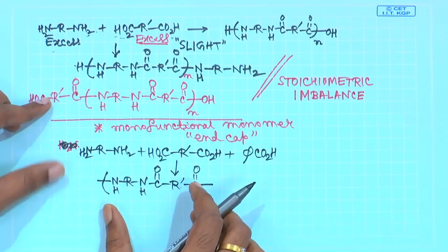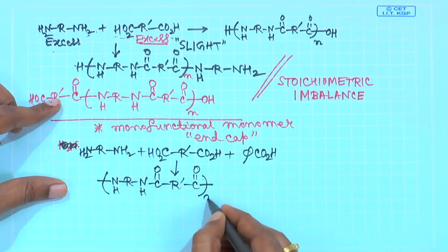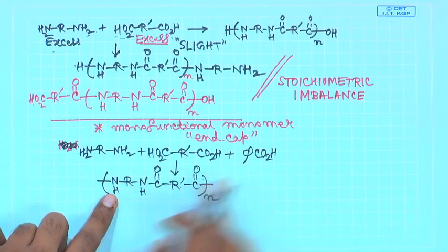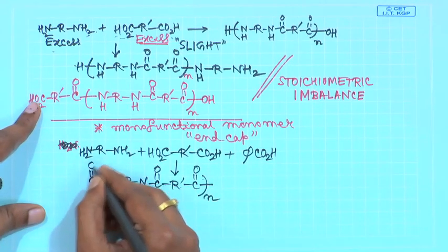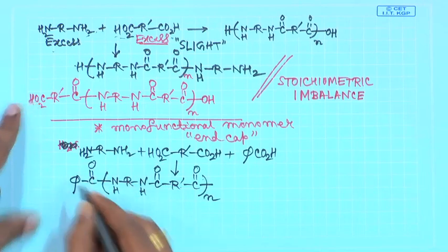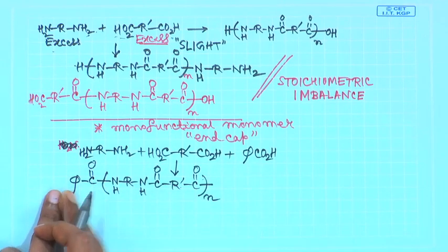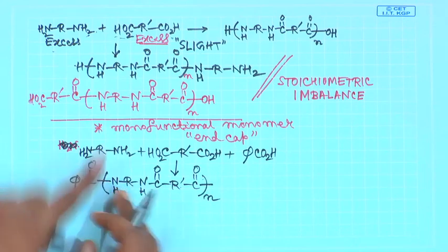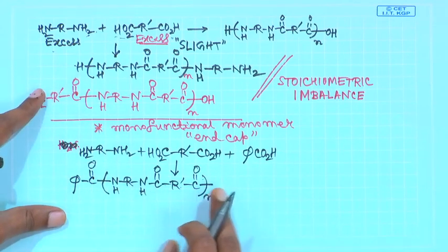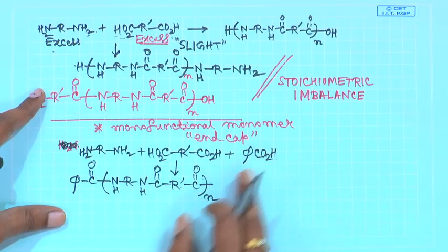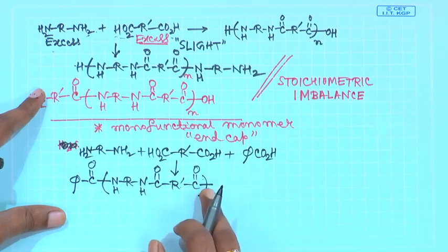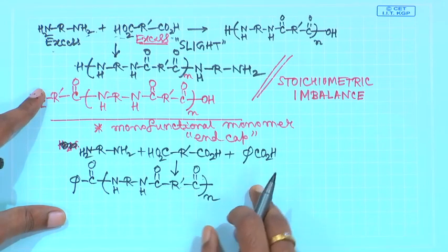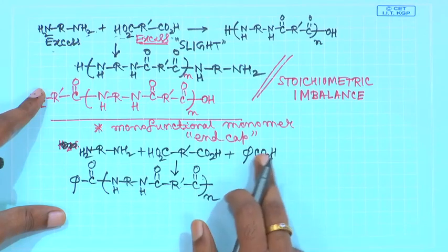So, you draw the repeat unit like this. Now, this side you have an amine, it will react with this carboxylic acid. So, it will form an amide and benzene ring. This side there is no function left because this is a monofunctional monomer, this has reacted. Now, this side you have an acid, this acid cannot react with this acid. So, then basically this acid, if you have to finish this particular structure, you have to put the amine again, amide bond here with this end capper.